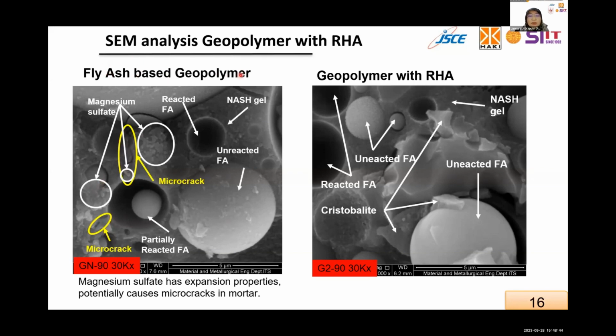This is the fly ash-based geopolymer, pure with fly ash, and this is geopolymer with fly ash where we add another silica source like rice husk ash. Micro cracks may occur due to shrinkage, and maybe because of the expansion of magnesium sulfate. As the porosity of the geopolymer matrix decreases and the density increases, it becomes evident that silica derived from rice husk ash, silica fume or blast furnace slag plays a very important role in sustaining continuous geopolymer reactions. Therefore, it inhibits the ingress of chemical attack into the matrix.